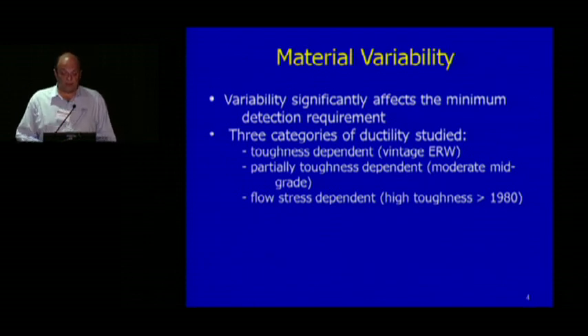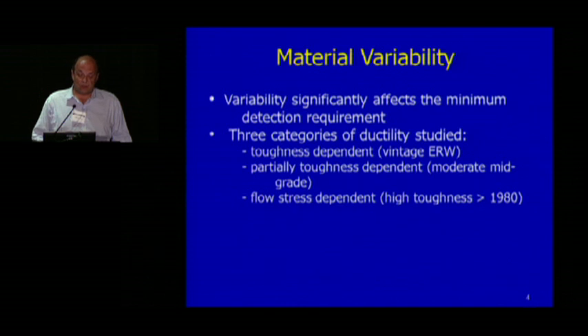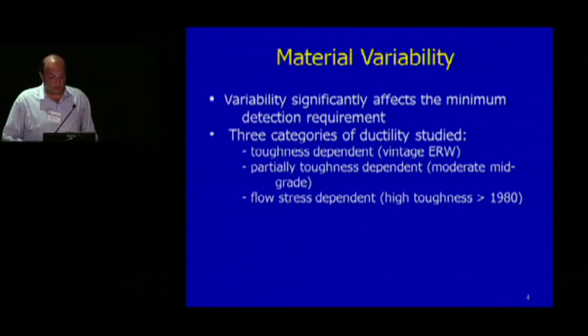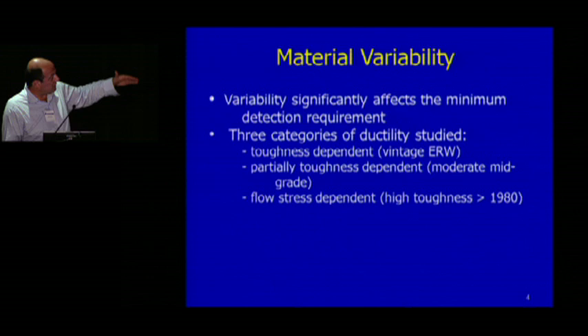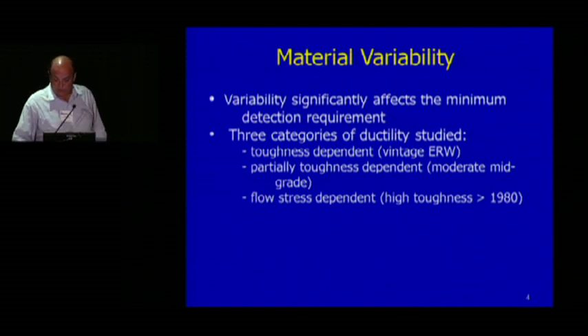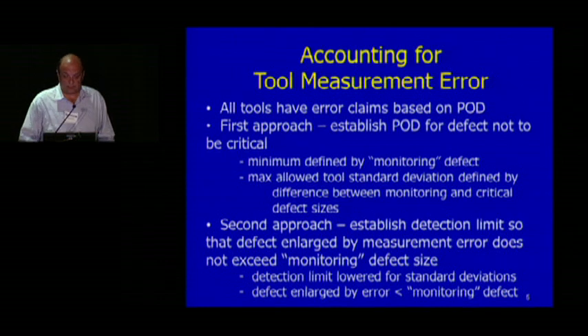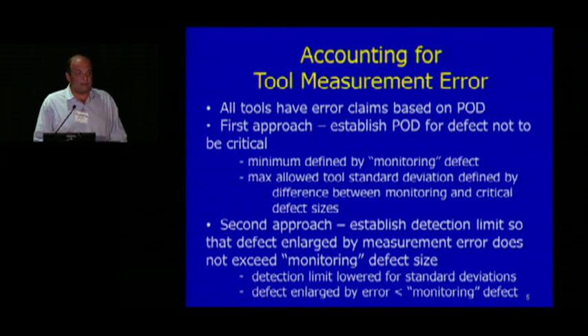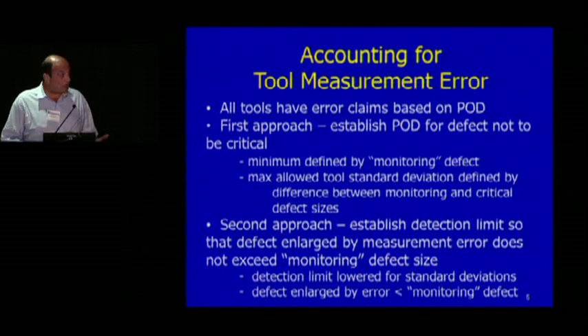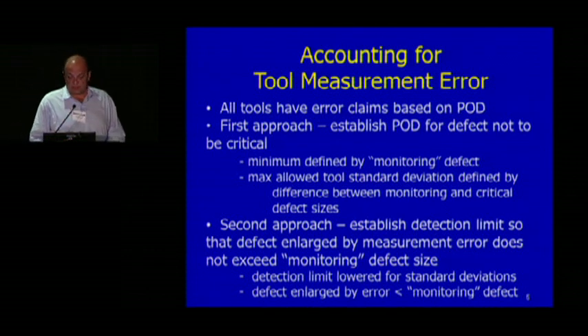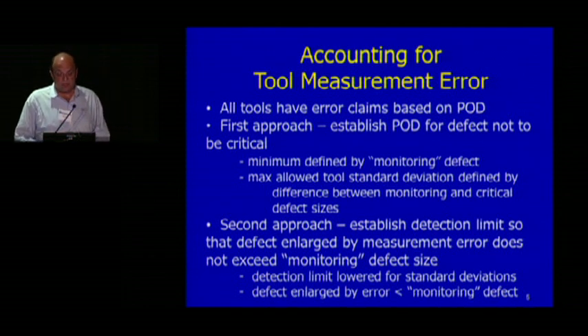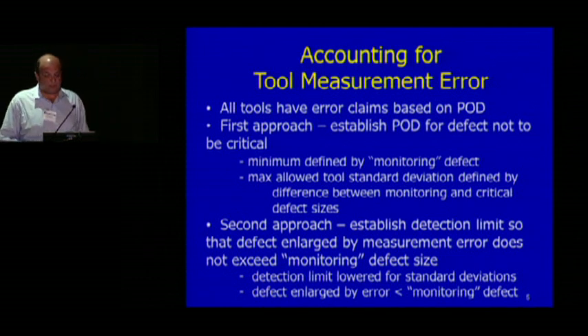Again, material variability obviously affects significantly the minimum detection requirement, and we consider 3 categories of ductility: toughness dependent, partially toughness dependent, and then the flow stress dependent, going kind of historically from the older to the newer type of materials. Oops, I went too fast. And coming to tool measurement error, all tools have an error in their measurement, typically specified as a probability of detection. So we took 2 approaches here. It's kind of a little design problem.